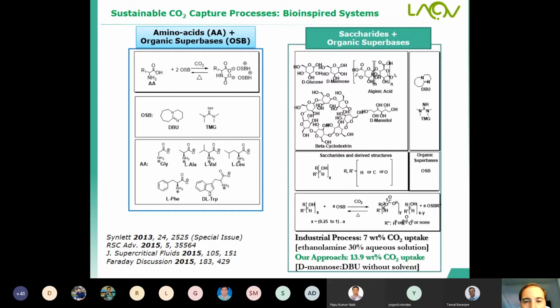We tried to test with glucose, mannose, mannitol, alginic acid, and beta-cyclodextrin, and in all of the cases, it's possible to prepare reversible polycarbonates using DBU or tetramethylguanidine as organic superbase. And here we can consider the number of hydroxyl groups, and the percentage of CO2 that it's possible to capture is higher. And we compare the industrial process.